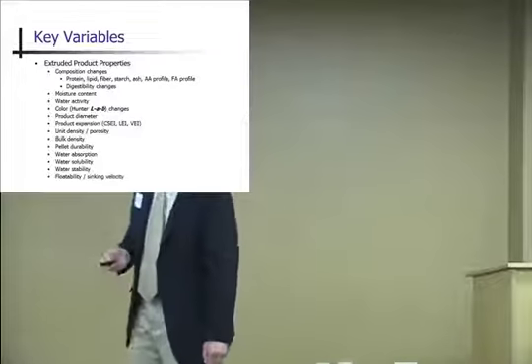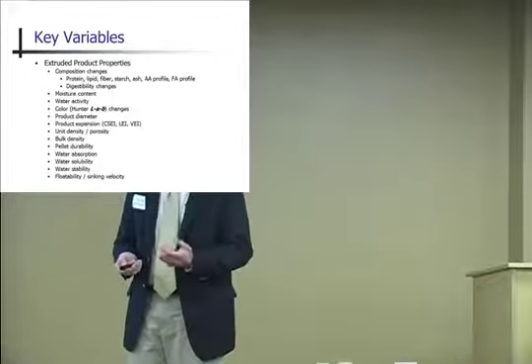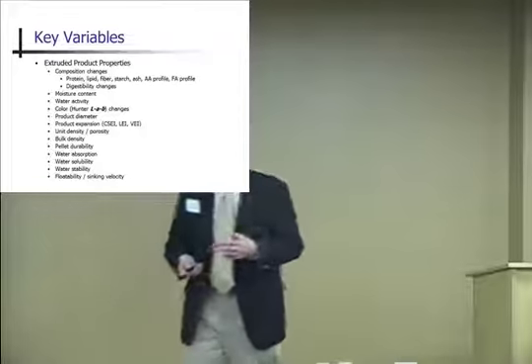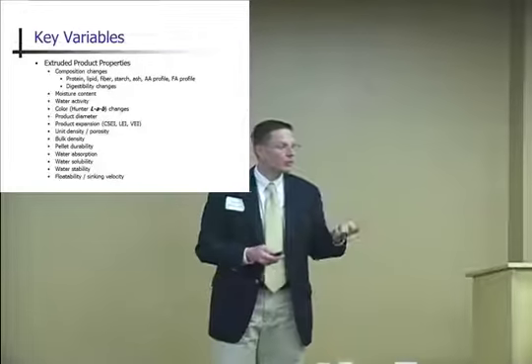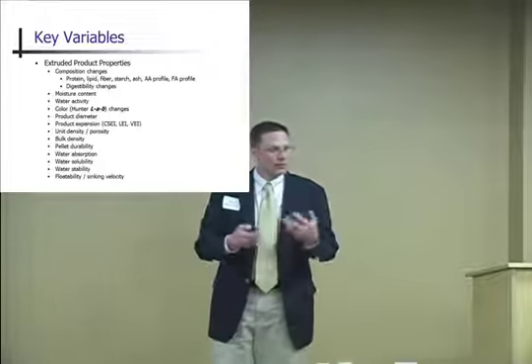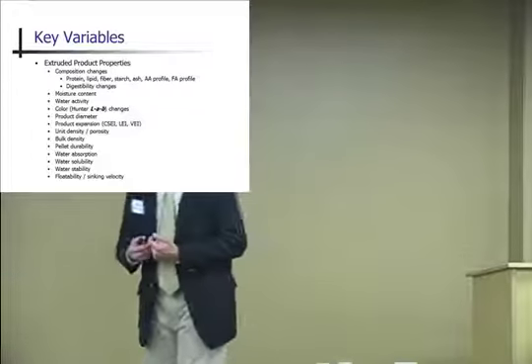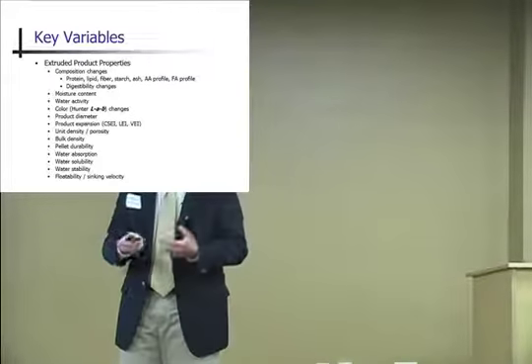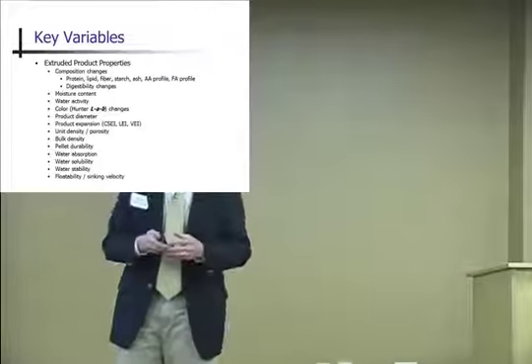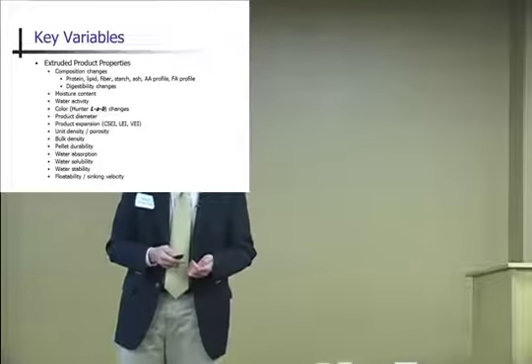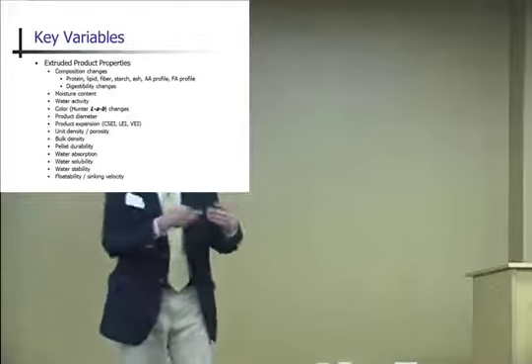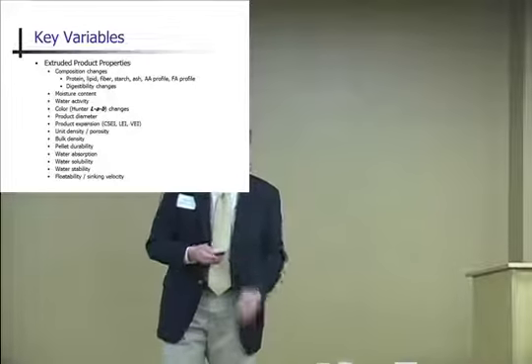What diameter are you looking for? What kind of expansion do you have? What kind of floatability? What kind of water absorption does that have when you put the pellets in water? You don't want the pellets to absorb water too quickly, because when that water starts to infiltrate that pellet, it's going to start to break the pellet down. And then the pellet is just going to become waste on the bottom of your pond or your tank.